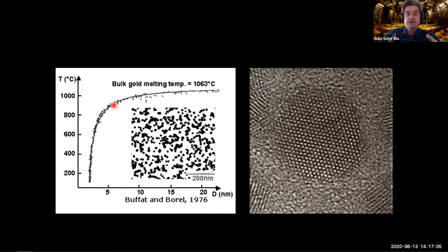This was made under a transmission electron microscope, and what you see here is a transmission electron microscopy image of one gold nanoparticle. You can see here some white spots. This is the space between the atoms. These dark dots here correspond to the gold atoms. What you see is the crystalline structure of a particle, and you can change the temperature and see when these atoms become disordered, and then you have the melting phenomenon.